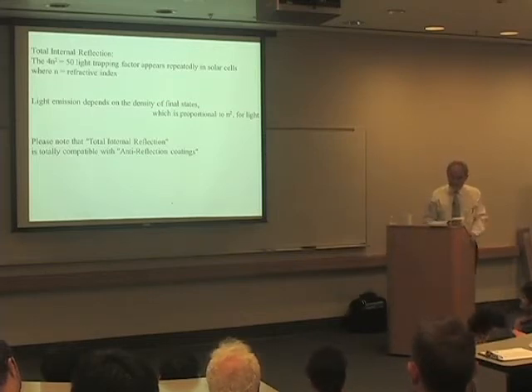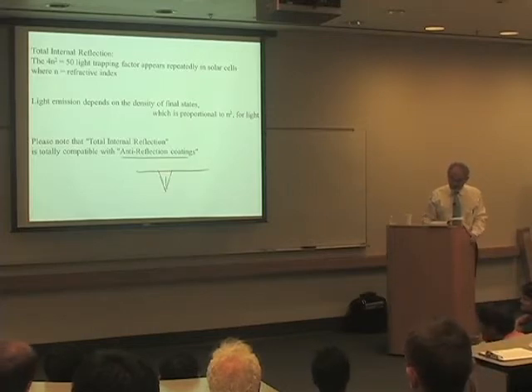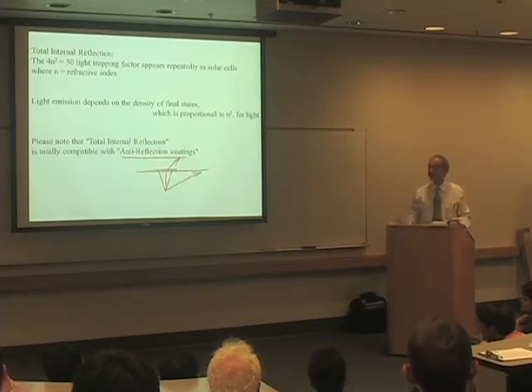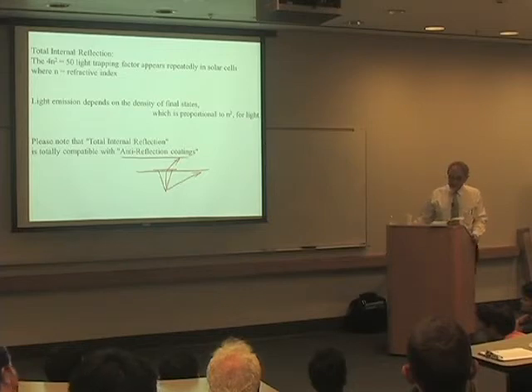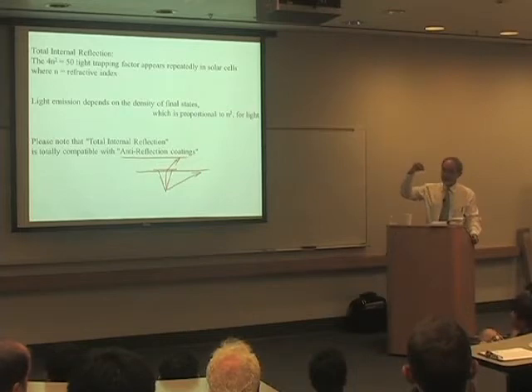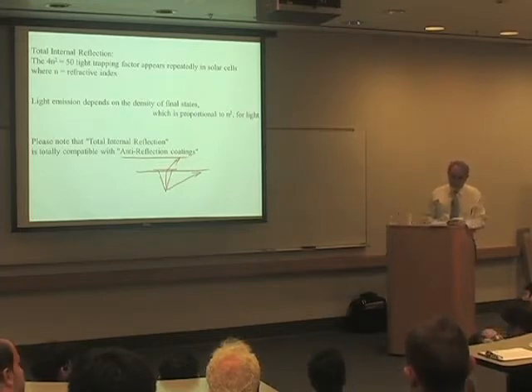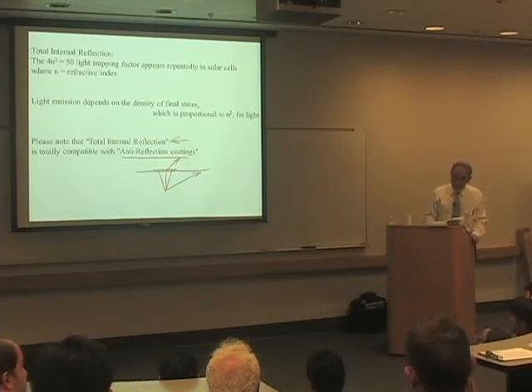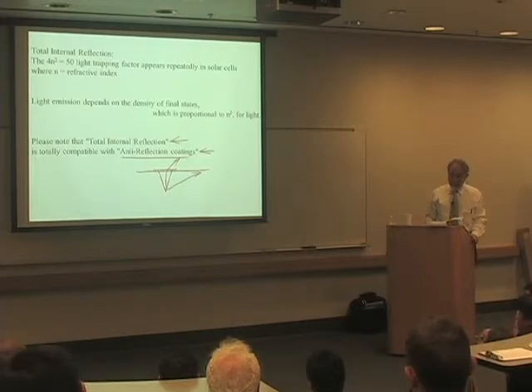The reason is the anti-reflection coating only applies to those rays that are within the escape cone. So there you better have an anti-reflection coating. But for the rays that are going to get totally internally reflected, nothing helps. The anti-reflection coating has no effect. The total internal reflection just depends upon the overall difference in refractive index between the active volume of the solar cell and the external world. The external world is index 1. And so, yes, an ideal solar cell has both total internal reflection and an anti-reflection coating.